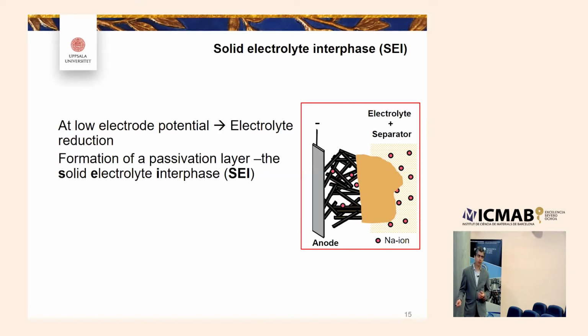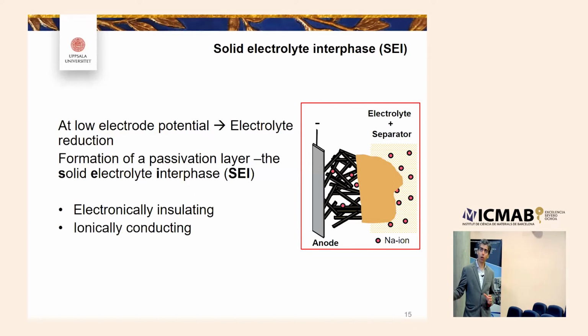This is, of course, a very schematic picture. In reality, SEI is a very thin layer, just a few nanometers of inorganic and organic species. This layer is supposed to be electronically insulating—it should not allow electron diffusion or transfer, but at the same time should allow ion diffusion and transfer from the electrolyte to the electrode.